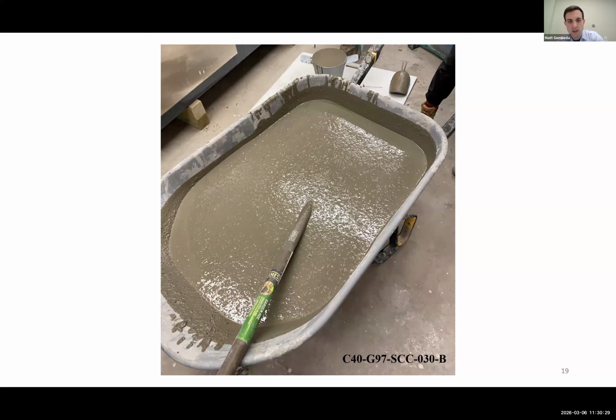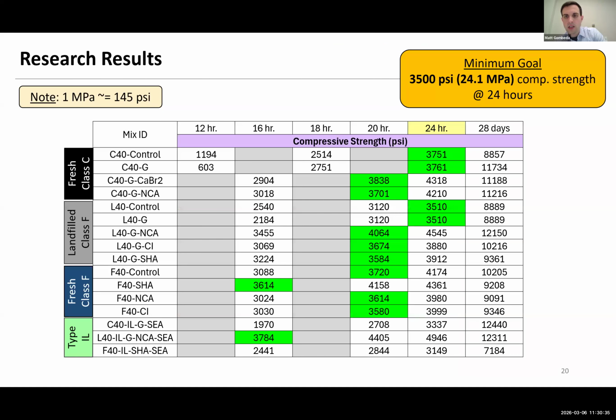And here's a picture of our finished SCC mix in the wheelbarrow, or one of them anyway, straight out of the mixer. And so here's some results for compressive strength. So we had, again, the minimum goal was 3,500 at 24 hours. And wherever I have the light green is where we've hit that target. So for some of the mixes, actually for a fresh class F and actually did some type 1L mixes towards the end of the project as those cements were starting to replace the old type 3, we were able to hit our target within 16 hours in a few of the mixes.